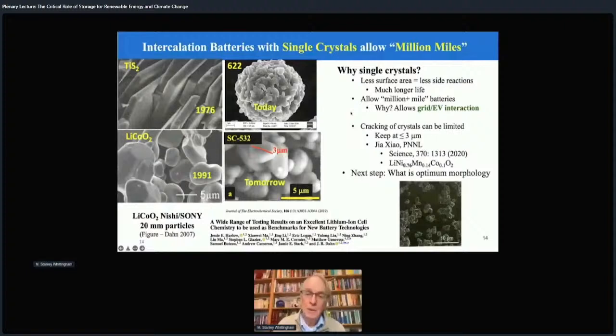Issue with the meatballs, why they don't last so long. These little particles, as the lithium goes in and out, they expand and contract. So where they're wedged up against each other, they will then cause the meatball itself to crack, not the primary particles, but that large meatball, which exposes fresh surface to the electrolyte, and it then gets side reactions occurring on